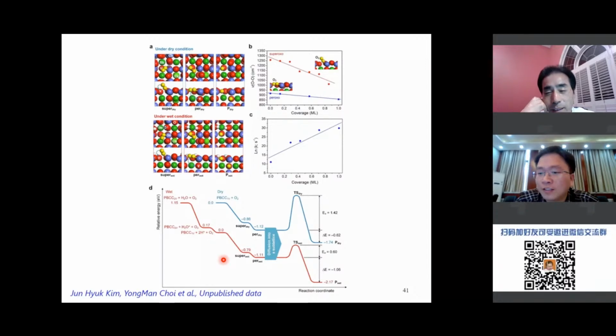BZCYYB depends on the composition. For the standard composition 1711, it means you get 10% of zirconia, 70% of ceria, 10% of yttrium, and 10% of ytterbium. Okay, so that's the standard composition for high conductivity. That one will be less stable against CO2. It depends on the concentration. If you only have a few percent of CO2, it might be okay. But as you increase the concentration, BZCYYB 1711 is no longer stable in CO2. It also depends on temperature.